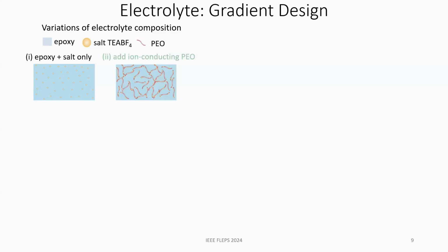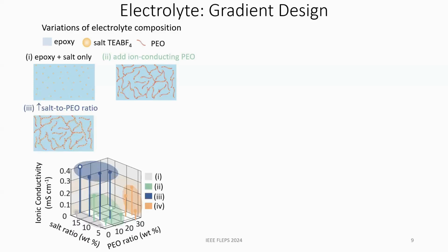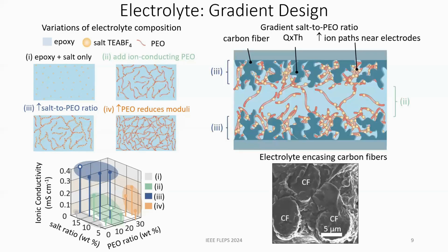So we also added the ion-conducting polymer, PEO. So PEO adds percolation networks and helps boost access to the electrolyte salts. And then we played with different variations of this formula and found that if you have a higher salt ratio, you'll have a high conductivity but lower strength. And then if you increase the PEO a lot, it still reduces the strength overall because it's not as viscous as the epoxy. So we came up with the gradient electrolyte.